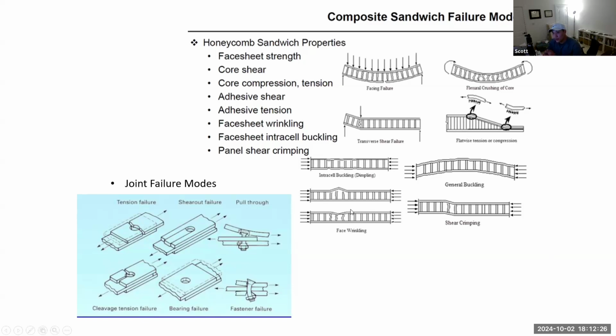And on top of that, other things you've got to check for are the joint failure modes, right? Because those parts are all connected to one another with fasteners. It's either bonded or mechanically fastened, right? And typically for composites, the critical failure mode is actually at the joints, okay? So the big things are pull through, as I mentioned before in the previous slides, where the countersunk head is pulling through the laminate under a high tension force, or bearing bypass. As the parts are bearing along each other, bearing is a typical critical failure mode for composites as well. And then there are these other types of failure modes which are not as critical typically.